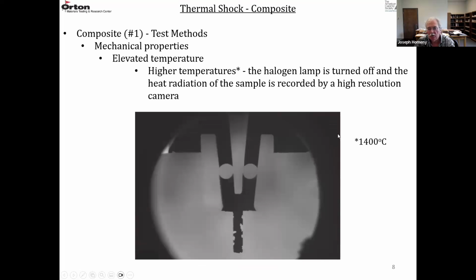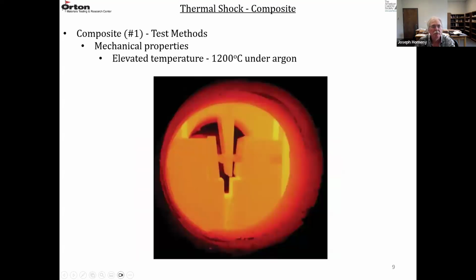Then at higher temperatures, greater than 1400 degrees C, you don't need the halogen lamp. There's enough heat radiation to see the setup. So this is what you see at higher temperatures. Again, you can see the wedge now, and then the cylinders, and then the transmission wedges, and then the crack. So you can monitor the delta, the crack displacement as you load it.